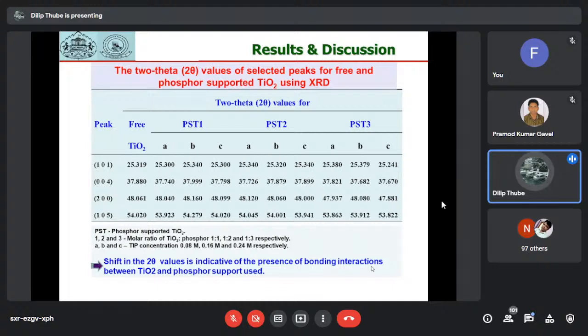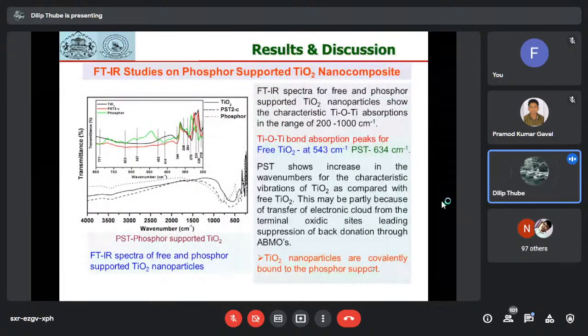So this slide shows the 2 theta values, and the 2 theta value shows a shift, and this shift is clearly indicative of the presence of the bonding interactions between the phosphor support and TiO2 materials. This is evident from the infrared spectroscopic studies of the phosphor supported TiO2 materials. If you look at the slide, the infrared spectra of the pristine TiO2 material, phosphor material, as well as phosphor supported TiO2 material is mentioned. In the inset, we have mentioned all the three.